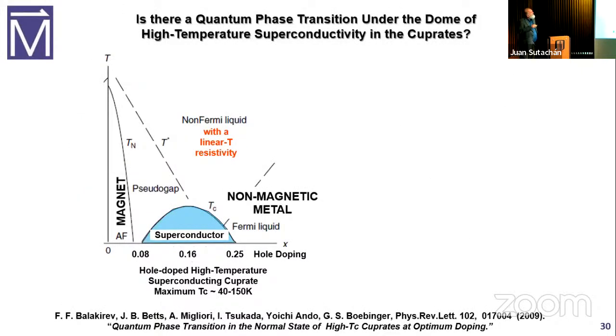Well, we go back to the high temperature superconductors. The magnetic phase transition is way over here. This pseudogap phase, there's something going on there. We don't fully understand it, but it does look like a phase transition coming down. And this material superconducts at temperatures that are more than twice any of those others, in some cases a factor of 100 higher temperature than those other materials I showed you. So maybe the differences here are the reason that these high temperature superconductors superconduct so well.